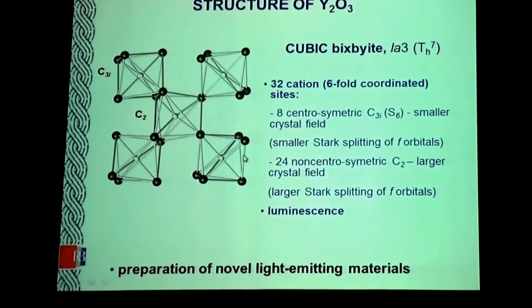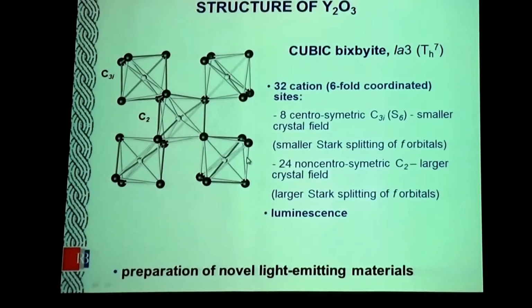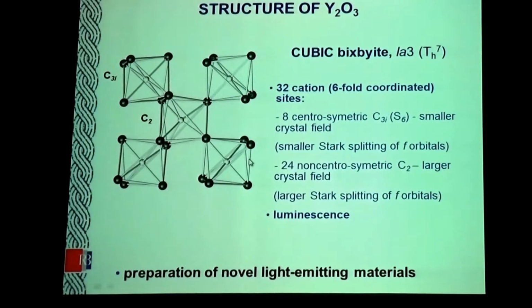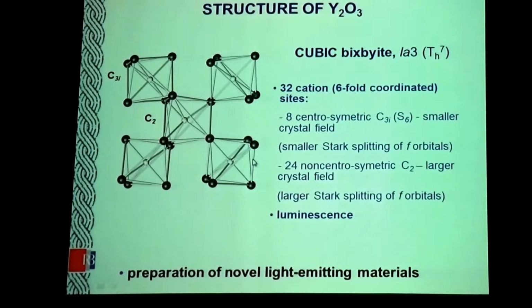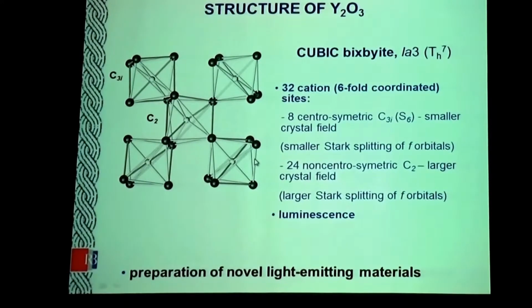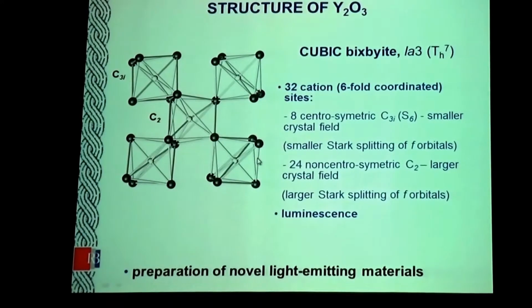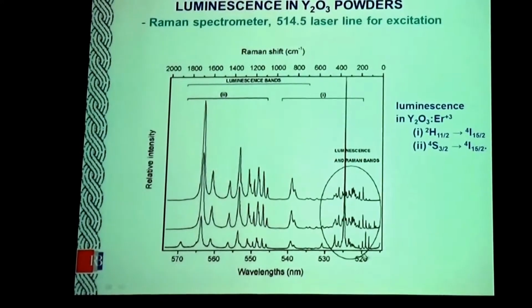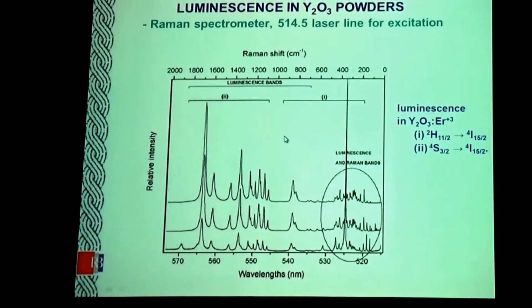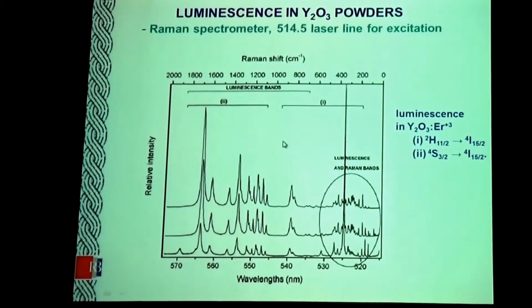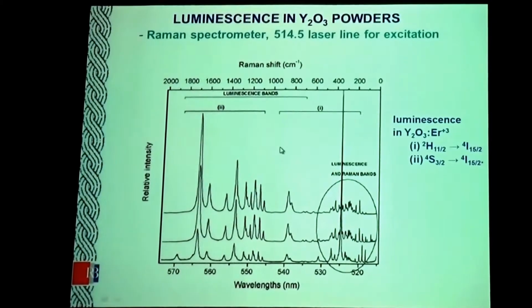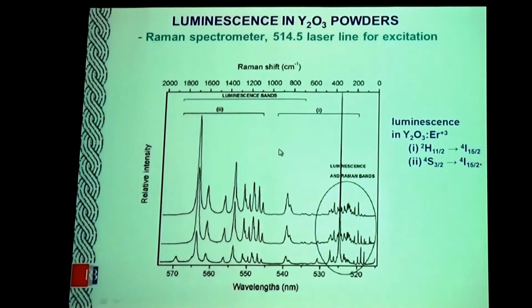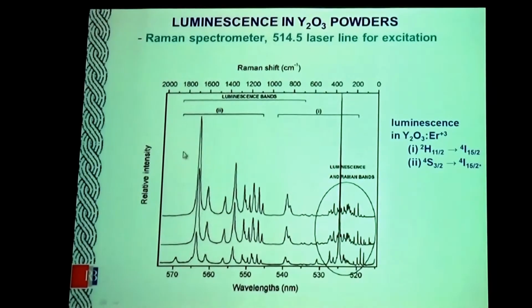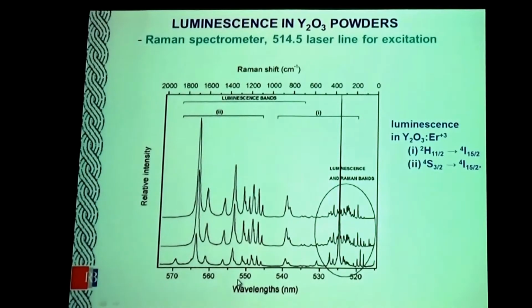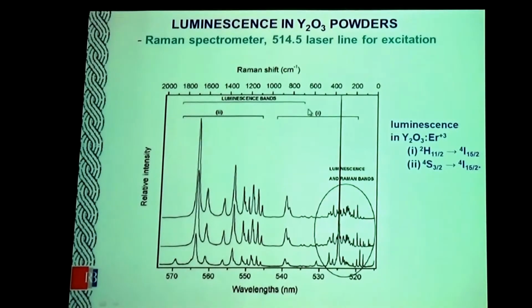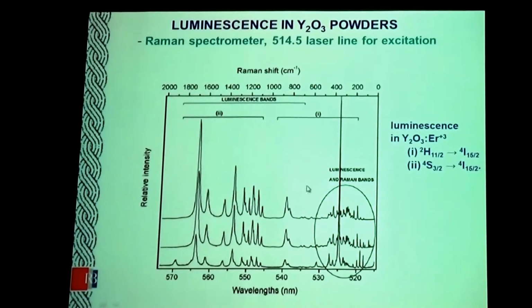So even if you have, for example, one ion of erbium or holmium or any other rare earth, in a whole large crystal with millions of atoms, you will have stark splitting, and you can observe electronic transitions between f orbitals. So it looks in the spectrum like this. This was a yttrium oxide compound, 99.99% pure. There is a very small amount of rare earth oxide which produces splitting of f orbitals, and we observe a very intensive luminescence band in the Raman spectrum.